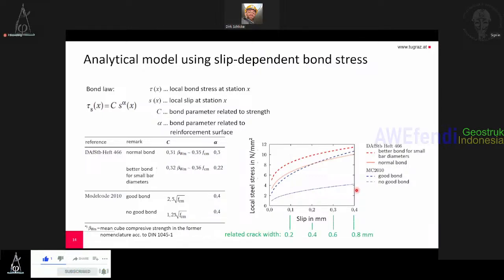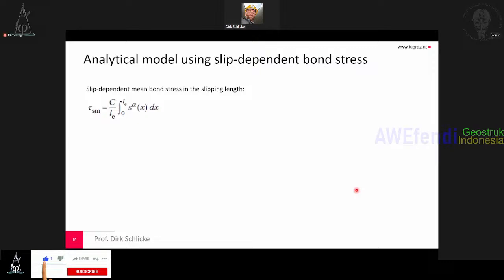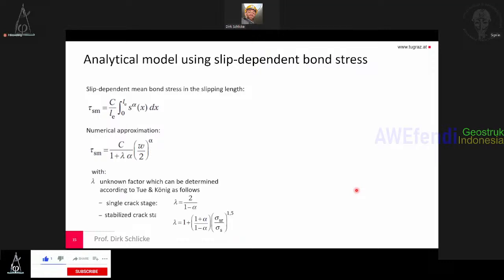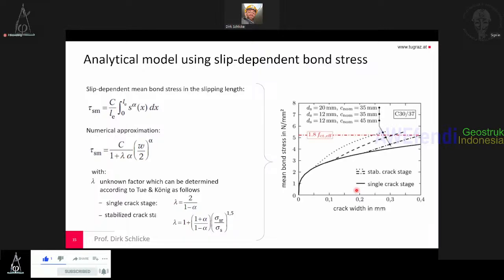This slip can be related to a crack width, namely if there's slip to one side, there is also the slip to the other side, and 2 times the slip is the crack width. This can then be averaged to a mean bond stress in the slipping lengths. There's a numerical approximation presented by Tue & König, I think in 1985 or something like this, which can be applied. And if you use this, you see the mean bond stress increases with the crack width. Small crack width, small bond stress, large crack width, larger bond stress. And if you change the crack stage to go from single crack stage to stabilized crack stage, this increases additionally.